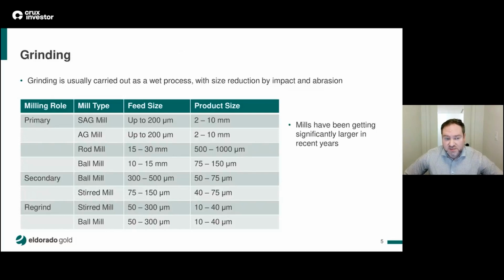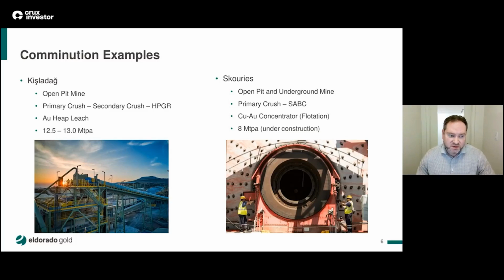Grinding is usually carried out as a wet process, and the size reduction of the particles is carried out by impact and abrasion. I've listed here some of the typical mills that we'll see in flow sheets, from very, very large SAG mills and AG mills, down to the ball mills and stirred mills that we see typically being used in secondary grinding or in regrind applications. One of the things that's been of note recently is these mills have gotten significantly larger, from the stirred mills to the SAG mills and ball mills, to allow for much larger throughputs with fewer parallel processing lines. Just a few examples from operations within Eldorado.